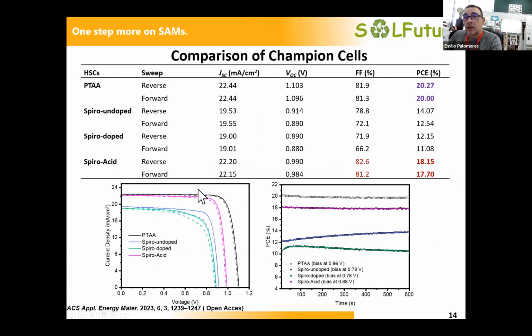So here is the IV curve. The nice thing about working with the SAMs is that you avoid this process called hysteresis, which is rather important when you work on modules. You have hysteresis, or large hysteresis, in modules. This is really an issue. When you work with the self-assembled monolayers, the hysteresis is almost negligible. And the efficiency, and this is real efficiency, is quite good. I mean, for 600 hours at bias, you have sealed devices, but not in nitrogen, just measuring in the sealed devices. It's rather, I believe, remarkable.